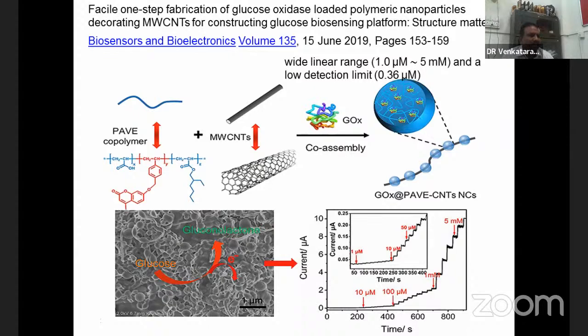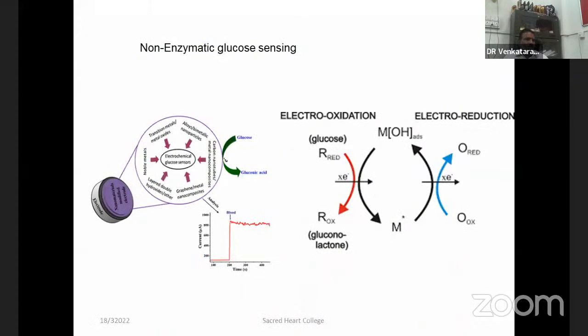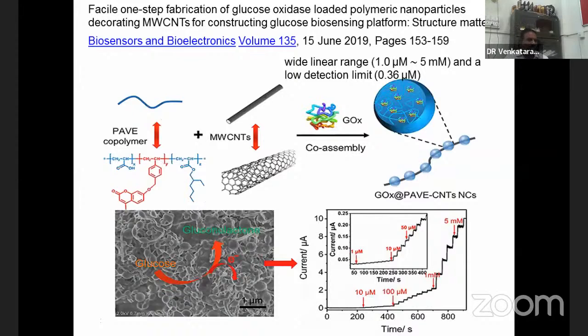And the lowest detection limit is the lowest concentration to which your sensor responds, which is about 0.36 micromolar. Recently we have also attempted using carbon dots, gold nanoparticles and zinc oxide nanoparticles along with the enzymes. But we are not much interested in using enzymes. Rather, we try to develop a glucose sensor which avoids glucose oxidase.